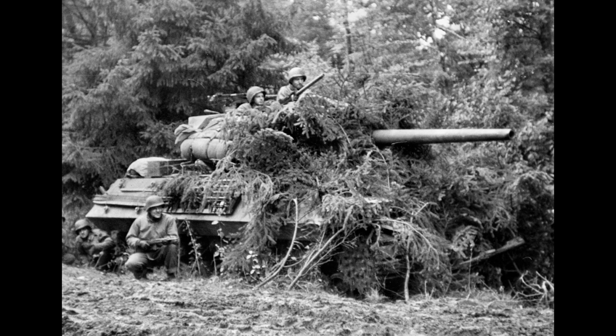Post-war examination of captured German armor by American and British technical intelligence teams revealed the extent to which German armor quality had deteriorated. A Panther tank captured intact near Aachen in October 1944 and shipped to Aberdeen Proving Ground for testing showed armor with Brinell hardness ranging from 210 to 280 across different areas of the same plate, a variation that indicated inadequate temperature control during heat treatment. Earlier war Panthers tested at Aberdeen had shown more consistent hardness values around 260 to 270.